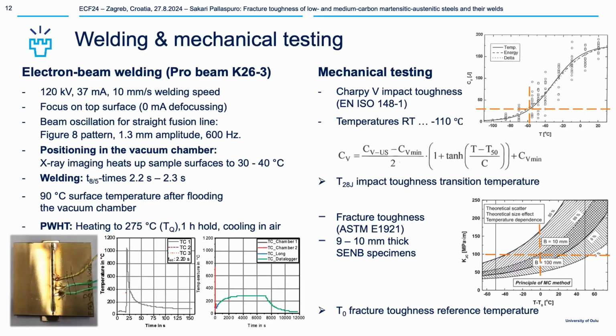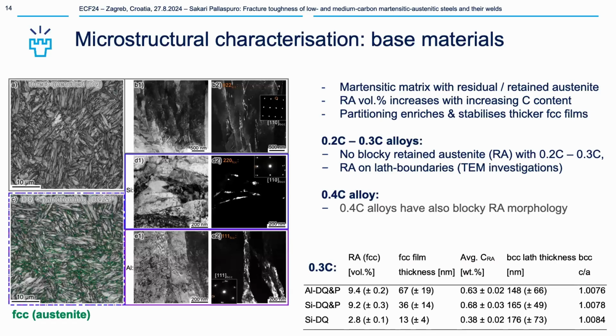We also did electron beam welding for these materials at the Technical University of Braunschweig, and we can discuss these details later after this presentation. Then fracture toughness testing according to ASTM E1921 with 3-point bend test specimens to get these reference temperatures. So what do we get?